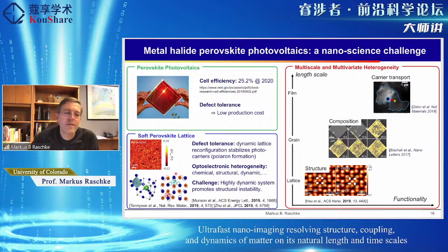And also it comes with an additional challenge that, in fact, this underlying soft lattice, which allows the polaron formation, also causes challenges, especially that this very dynamic instability of the lattice then also leads to a lot of structural heterogeneities. And this is from the atomic scale all the way to device scale, including compositional phase separations and other effects, which again would diminish the performance of these solar cells. And this is something which one wants to understand and see how to optimize this polaron stabilization and promote carrier transport without detrimental effects from phase separations or other non-desirable heterogeneities.